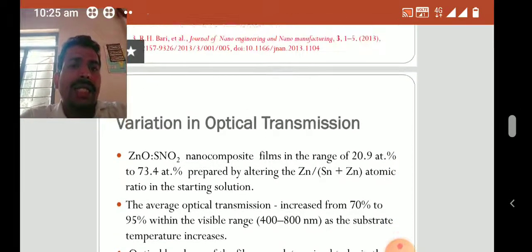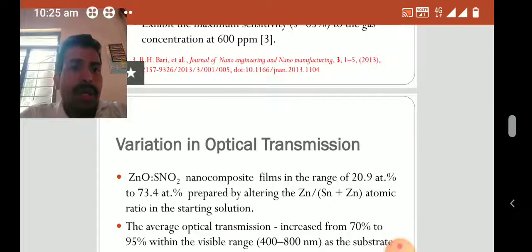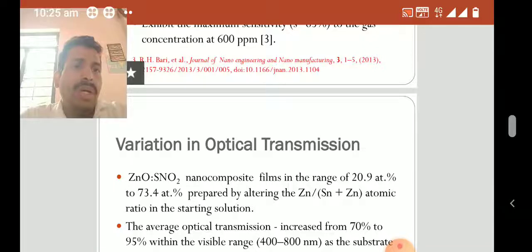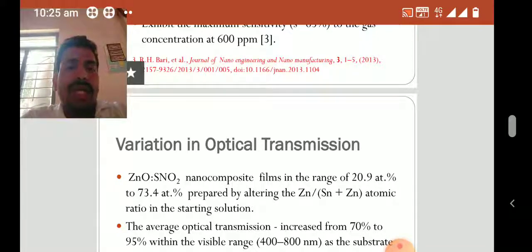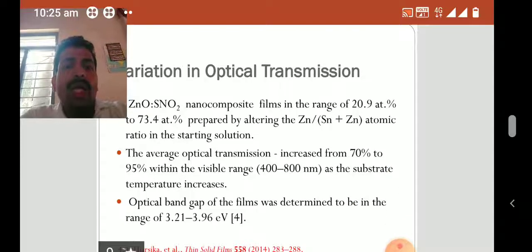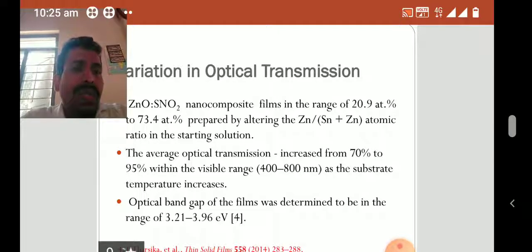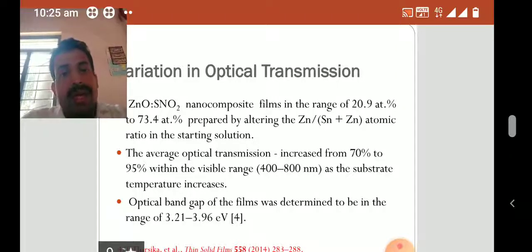In another study, let us consider variation in optical transmission. Zinc oxide tin oxide nanocomposite thin films in the range of 20.9 to 73.4 atomic percentage were prepared by altering the zinc oxide to tin oxide atomic ratio in the starting solution. The average optical transmission increased from 70% to 95% within the visible range, 400 to 800 nanometer, as the substrate temperature increases. Here, as substrate temperature increased, the optical transmission also increased. It implies that the optical band gap for the films was determined to be in the range of 3.21 to 3.96 electron volt.